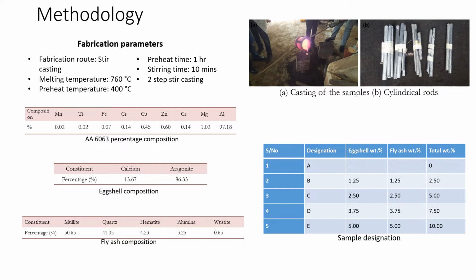For this route, the fabrication parameters include a melting temperature of 760 degrees Celsius, a preheat temperature of the reinforcement of 400 degrees Celsius, a preheat time for the reinforcement of 1 hour, and a stirring time of 10 minutes. For the stirring, the two-step stirring method was adopted.